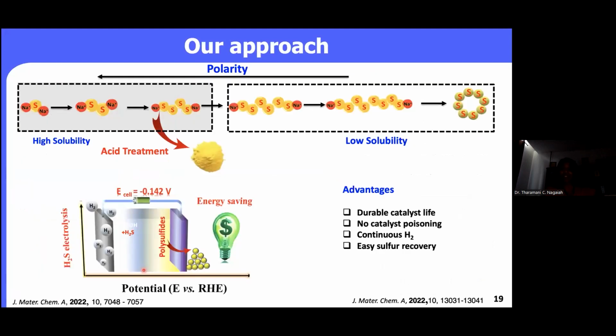And you can see here the corrosion of the catalyst, especially in the presence of H2S. Here, again, we are coming with an approach in order to avoid the sulfur accumulation. So what we are doing is that when we are doing the sulfur oxidation reaction, we are restricting the potential to only the lower order polysulfides, because these are highly soluble in water, so that we do not allow this polysulfide to deposit on the electrode surface. So again, the advantage is that continuously we can produce the hydrogen. And apart from producing the hydrogen, whatever polysulfide we are producing in the solution, we can extract by the acid treatment. This material can be utilized as a battery material as well.